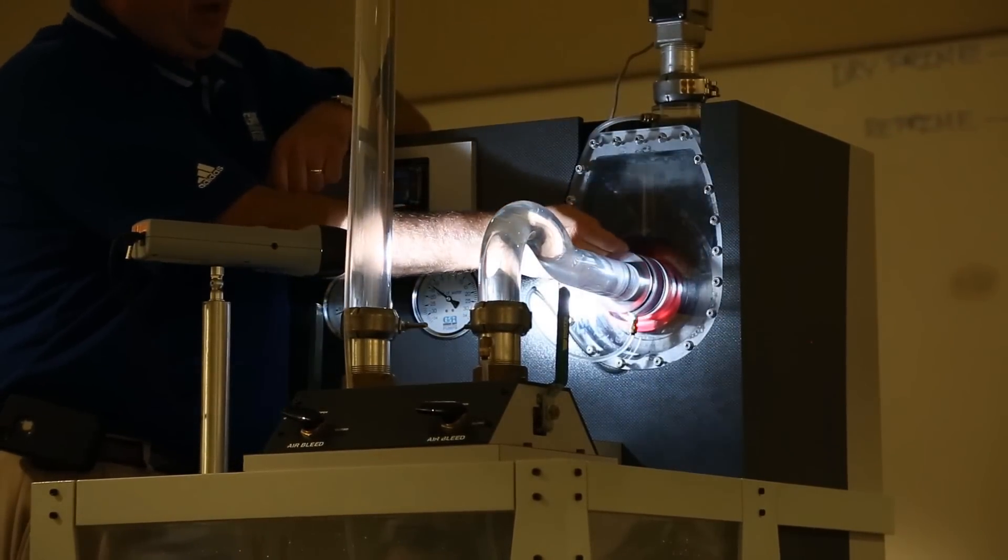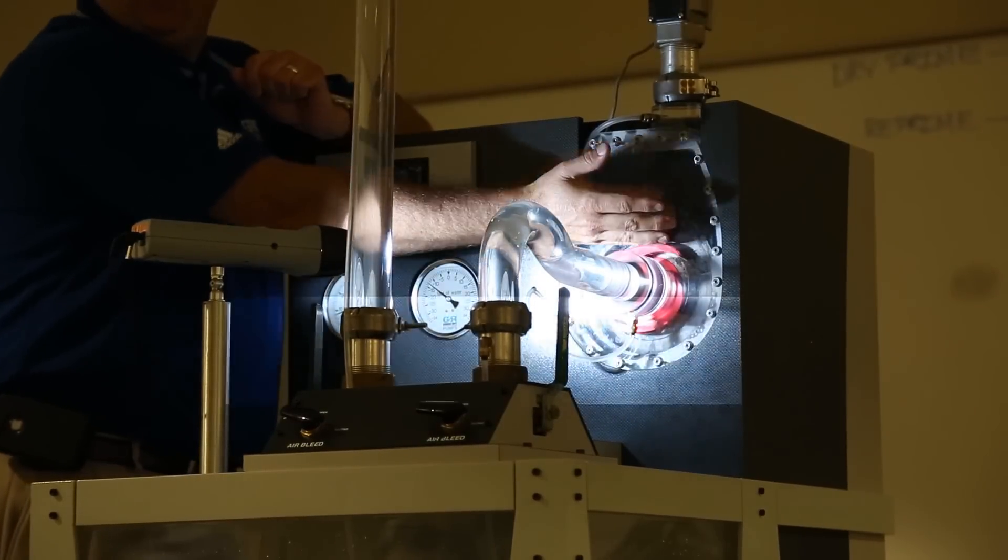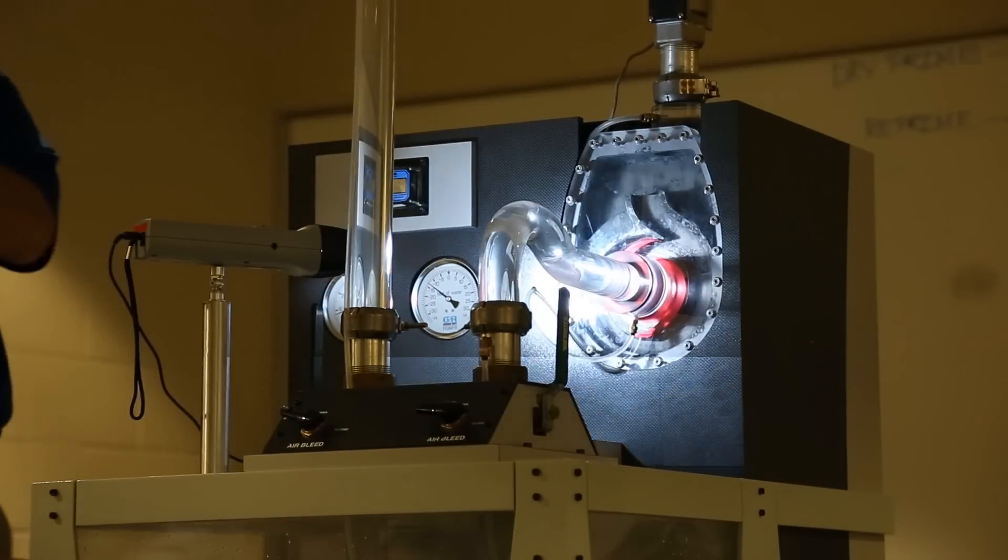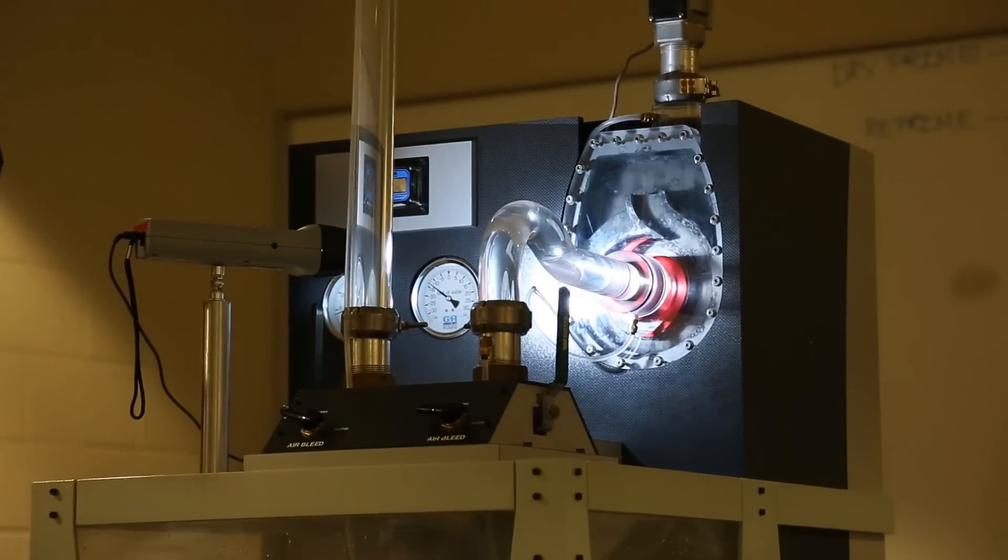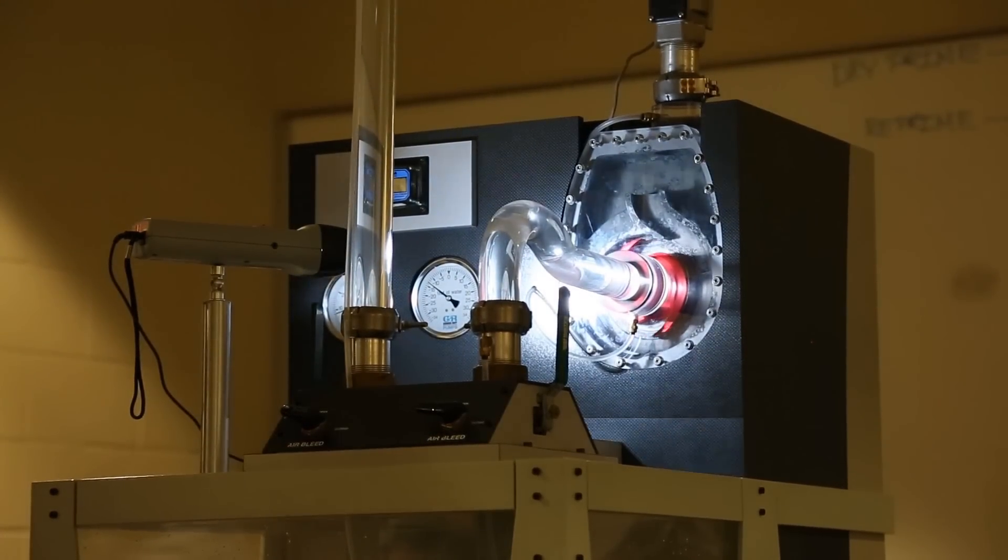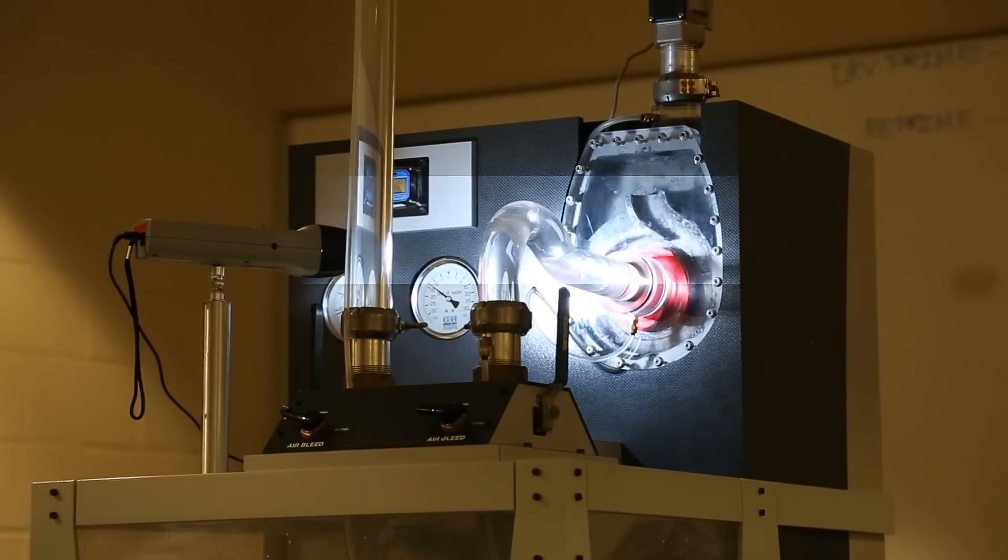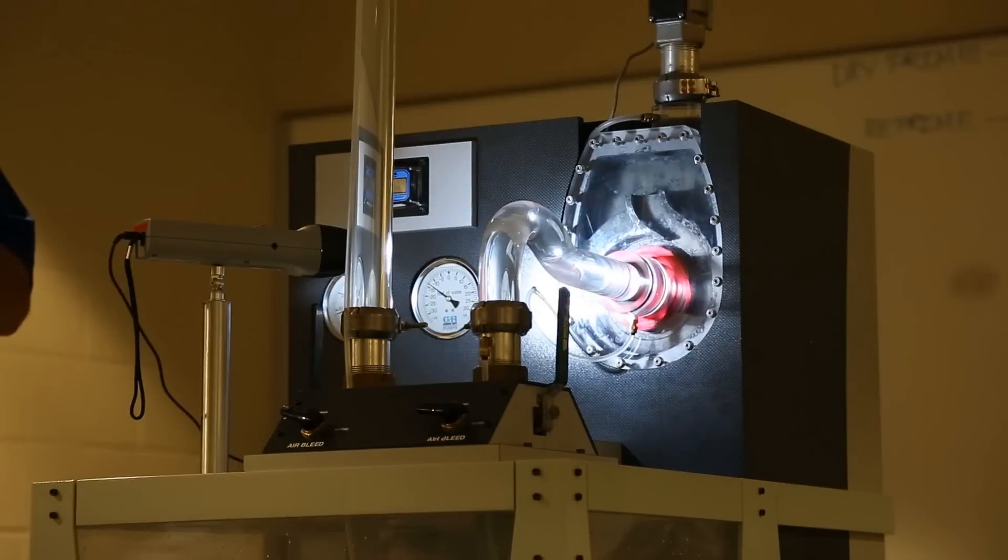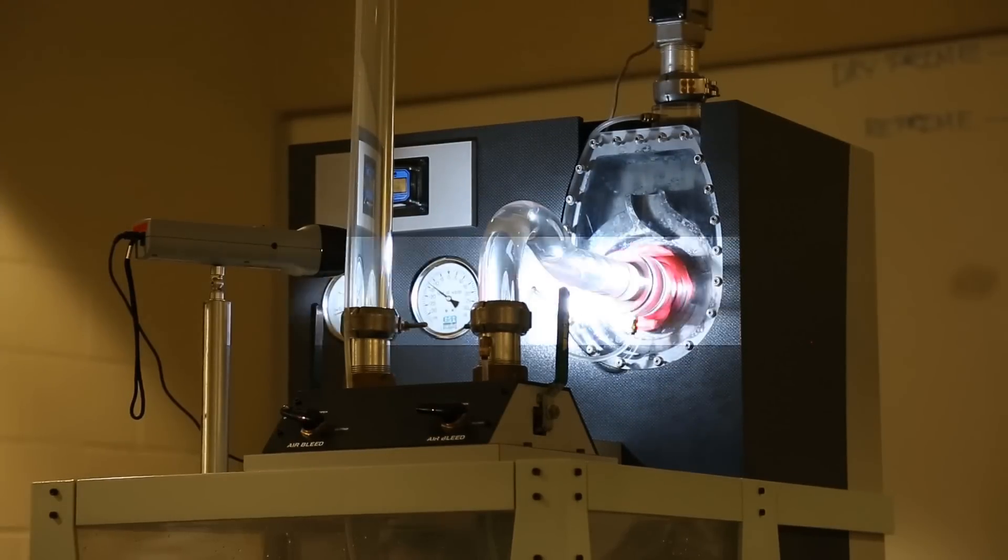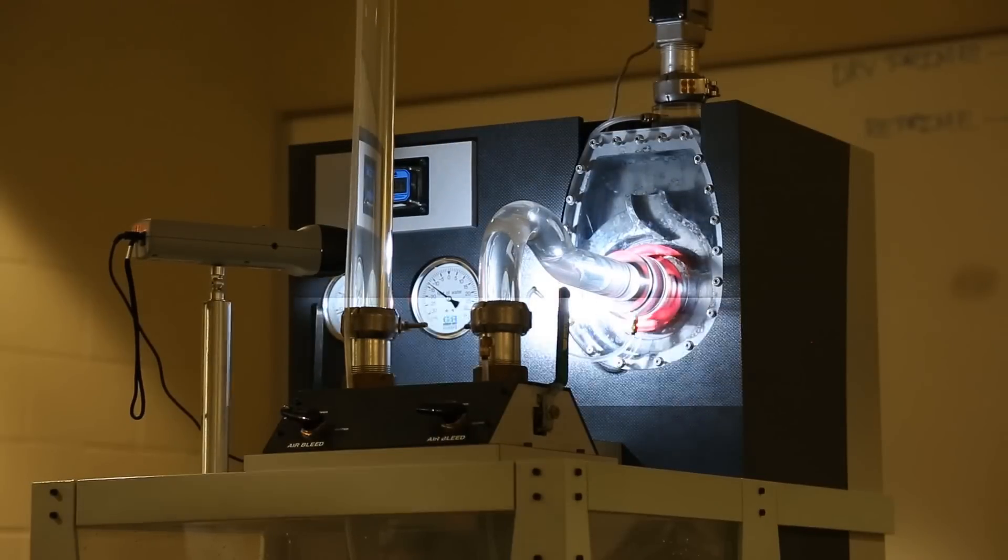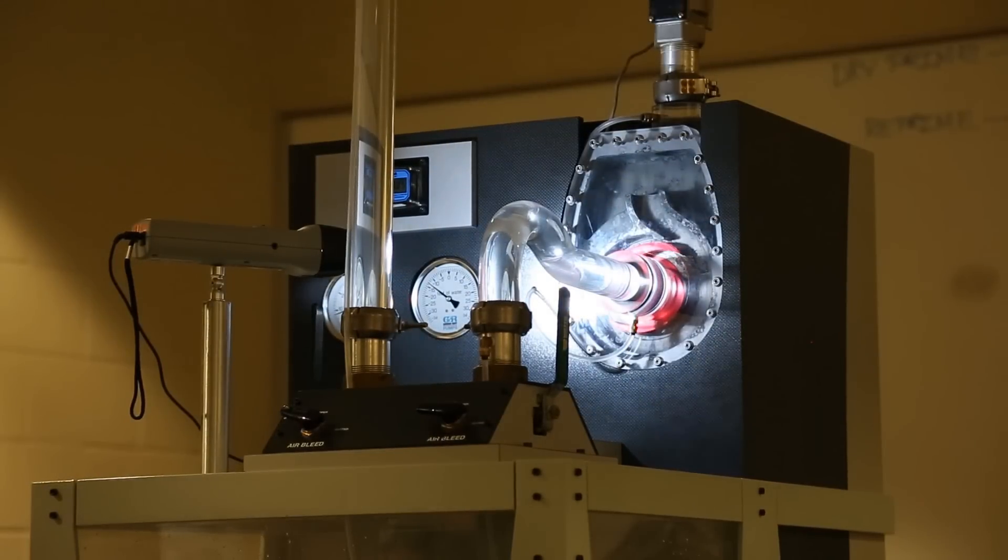As I get to the eye of the impeller, on the discharge side of this pump there's no restriction. So all of that liquid slows back down and those vapor bubbles implode back into liquid. And that's where the destructive force of cavitation is, when those vapor bubbles implode back into liquid. They give an energy discharge that's been measured between 80,000 and 110,000 PSI of energy release.